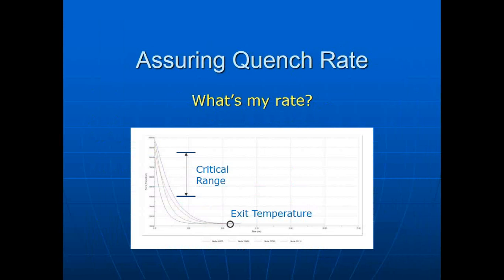So, what is my rate? One of the challenges of measuring rate is that the profile approaches water temperature as it approaches the exit of the quench. Here you see 4 different points on a profile, one an interior web, and then near the web, and then away from the web. And you see we're getting different cooling rates, and yet they all then merge at water temperature. And the entire profile comes out at water temperature. So I don't really have a tool. I have no measurement for rate when the profile is coming out cold. What I have to do is either extrude faster, or if I have a multi-zone quench, turn off some zones and have the profiles coming out hot before I can establish a rate.